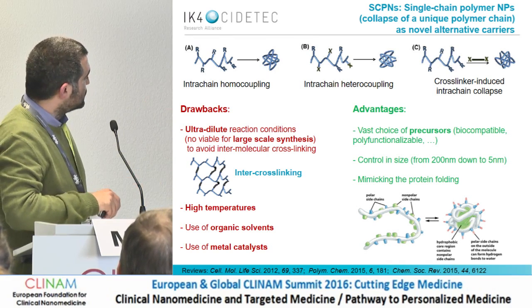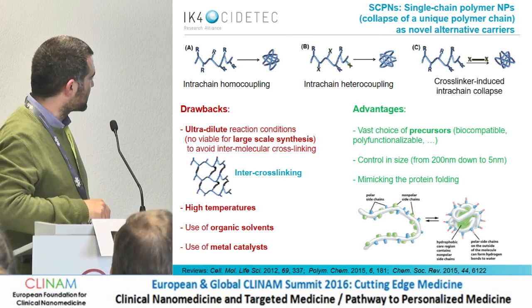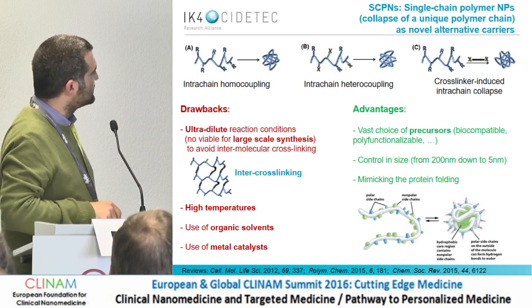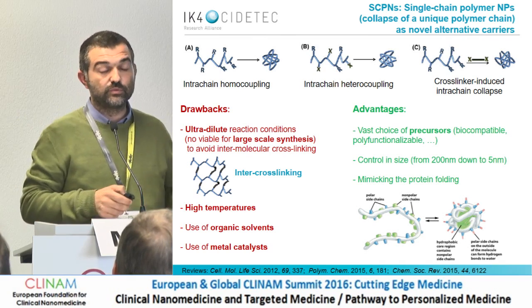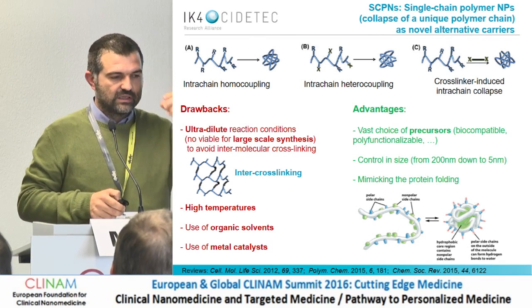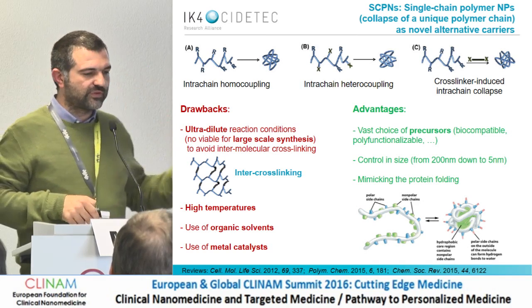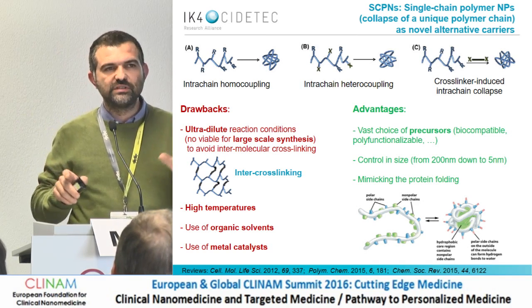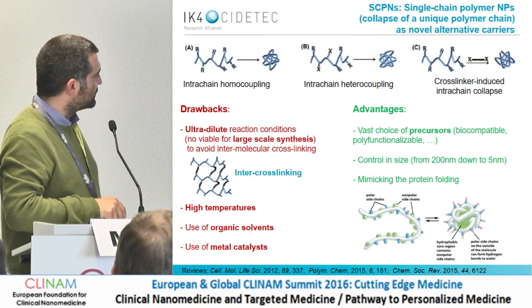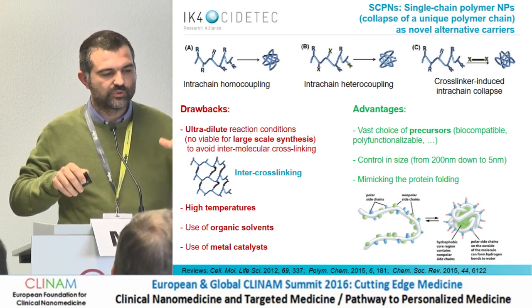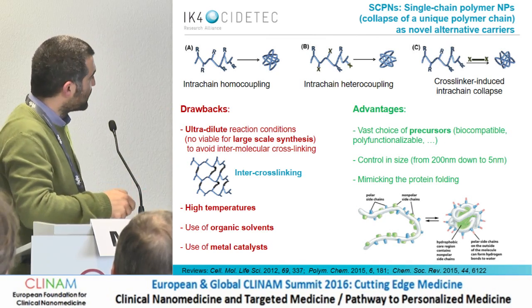Other problems are that usually this kind of nanoparticle is made in organic solvents using metal catalysts and high temperatures. On the other side, the advantage is that you can choose many precursors, especially if you work with polymer synthesis like RAFT, and you can control size very well — from 200 nanometers down to 5–10 nanometers — with different functionalizations. The general vision is to mimic what nature does with proteins, having a reversible folding process, though that is far from where we are now.